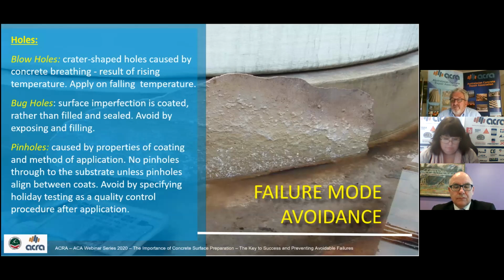We've got the likes of failure mode avoidance. We have a lot of problems with holes, bug holes and pinholes and things like that. Blow holes are the small crater-shaped holes caused by the concrete breathing. That's the result of the slab increasing in temperature. Usually it's magnified during exterior applications when exposed to direct sunlight. However, interior surfaces can experience the same phenomena, but usually to a lesser degree.